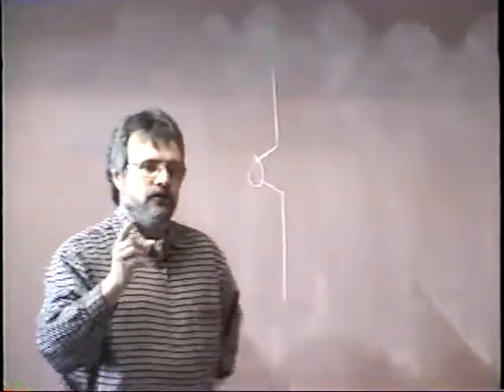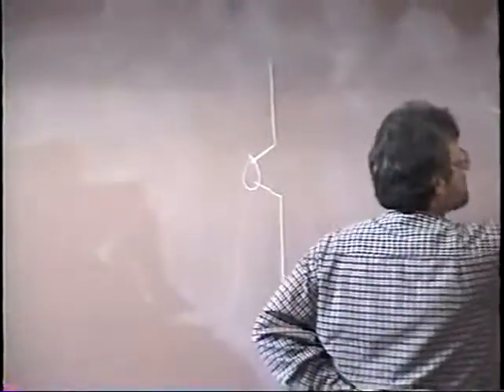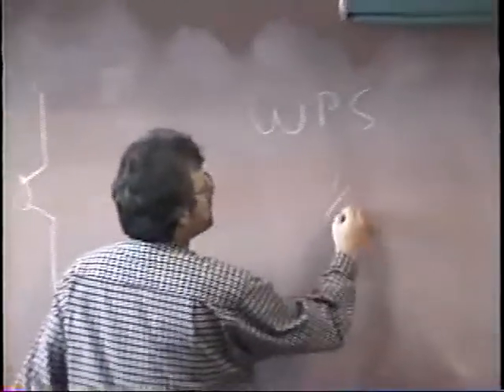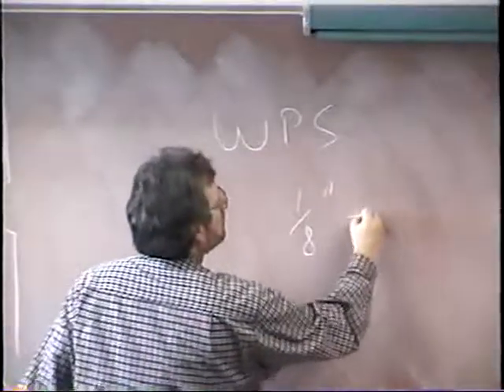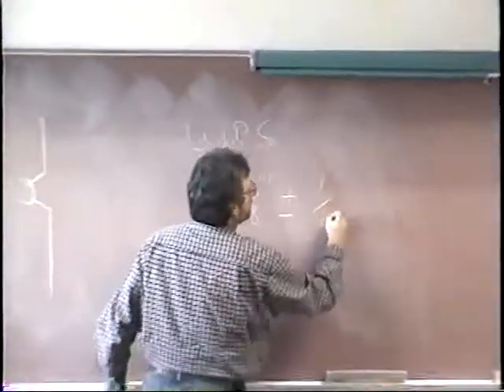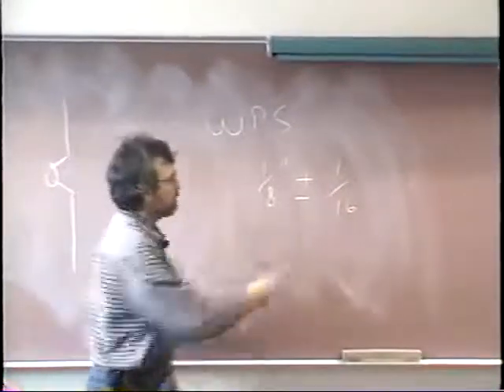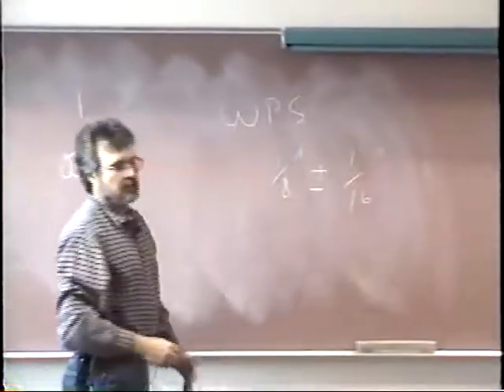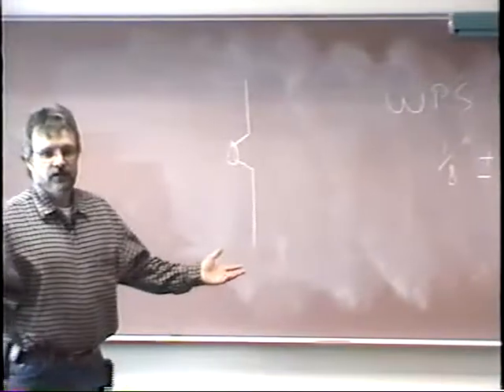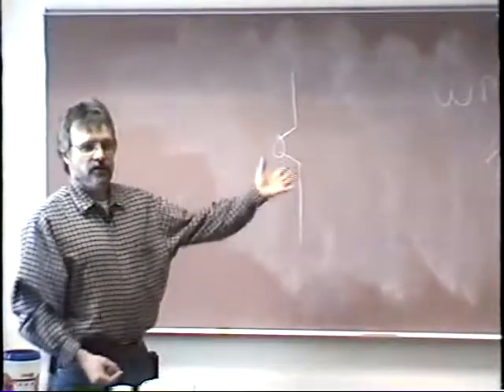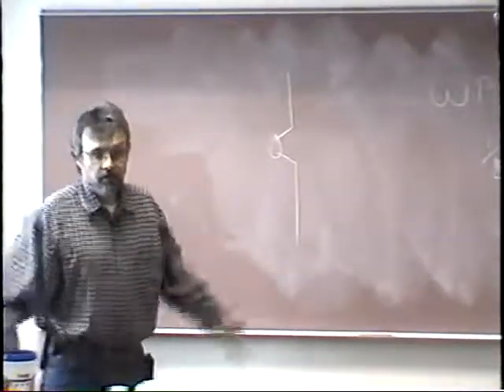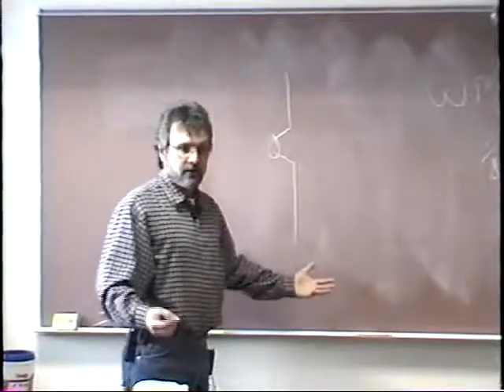But remember, when you're out there in the field, you're going to be working to a welding procedure specification, a WPS. That WPS is going to specify what that root opening should be. And usually it'll say something like 1/8 of an inch plus or minus 1/16. Anything beyond those limits, then the joint fit-up isn't acceptable and you're in violation of the WPS, and therefore by code you can't weld it. You've got to refit it.